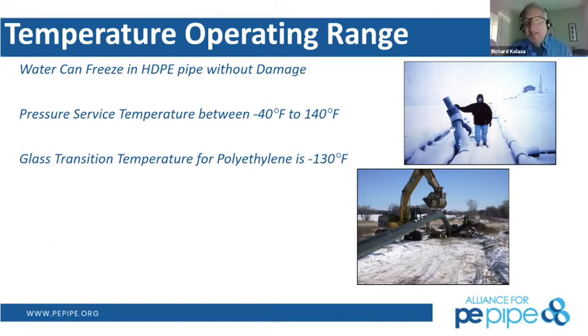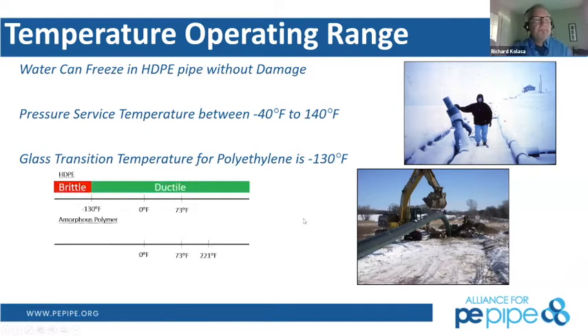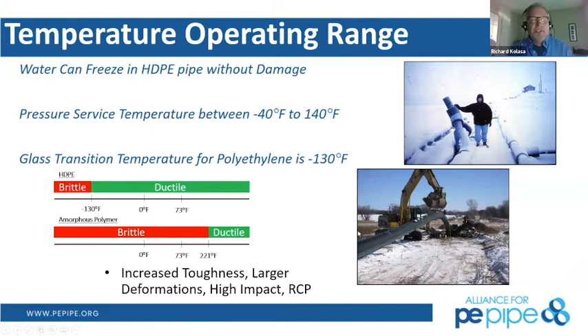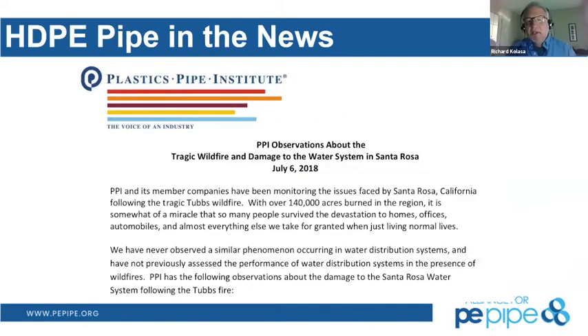Again, the glass transition for polyethylene is minus 130 degrees Fahrenheit, not an issue. It stays ductile. Does it become stiffer in colder temperature? Absolutely, because it's condensing. It will shrink on itself, so it becomes a higher density. So the energy to bend it will become higher, but it does not change your bend radiuses that we'll talk about a little bit later. Next slide, please. Oh, and here are the graphs. I think we've seen them already earlier, but that's just showing amorphous materials versus brittle. Your product is ductile, so it can handle this.